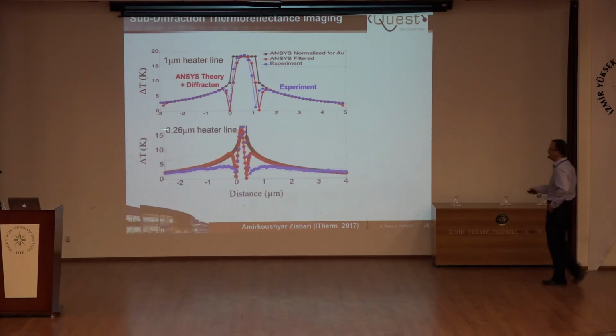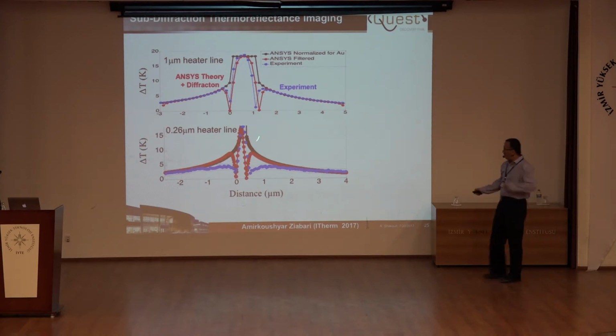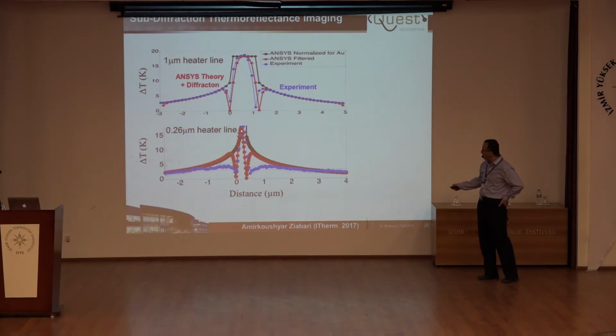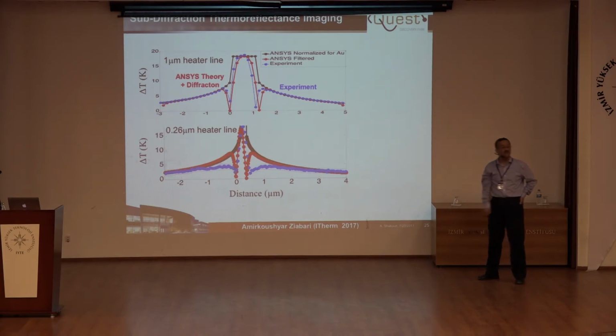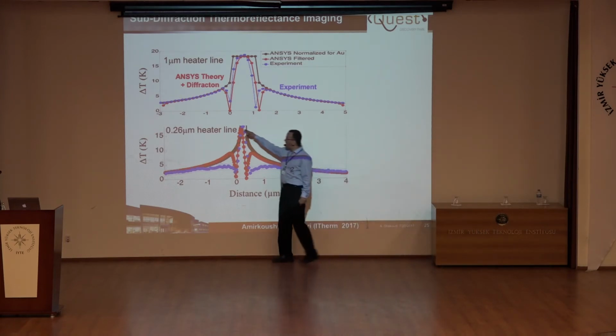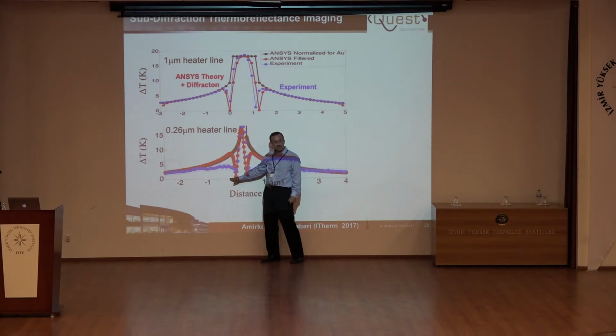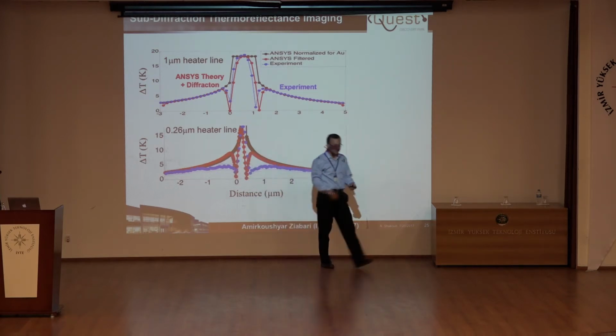If we do the same thing with a 1/4 of a micron heater line, what we see is quite surprising. The temperature on top of the heater line, theory and experiment match, but near the heater line, theory and experiment have significant deviation. Basically, if I have a heating of 15 degrees here, about a 1/4 of a micron away, Fourier's law tells me it should heat up about 7 degrees. We only measure heating of 2-3 degrees. This is outside the error bar, so definitely it is above.